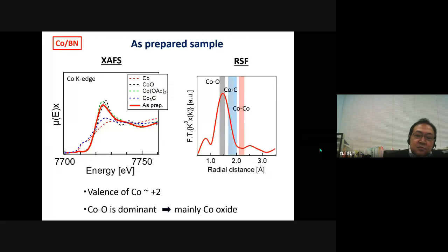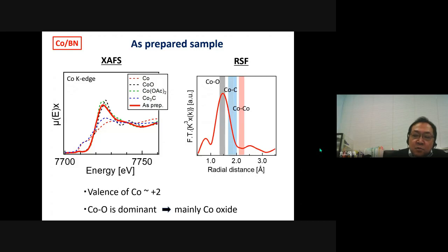The left figure shows the spectra of the as-prepared cobalt BN sample. For reference, the XAFS spectra of cobalt foil and cobalt compounds are shown as dotted lines. As you can see, the XAFS spectrum of the as-prepared sample was similar to cobalt acetate. This indicates the valence of the cobalt catalyst cobalt is about 2.